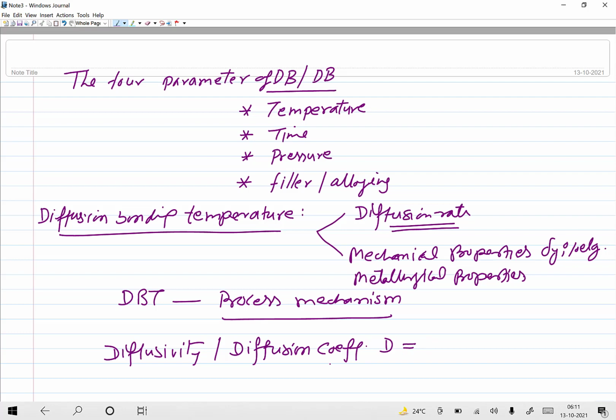temperature. So here if we try to understand the relationship between the diffusion coefficient and the temperature, the relationship is like this: D is equal to D naught e raised to the power minus Q by RT. D is the diffusion coefficient at a given temperature in Kelvin, D naught is the proportionality constant, Q is the activation energy for diffusion, T is the absolute temperature, and R is the gas constant.